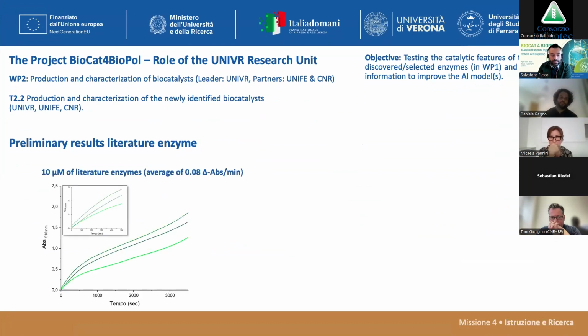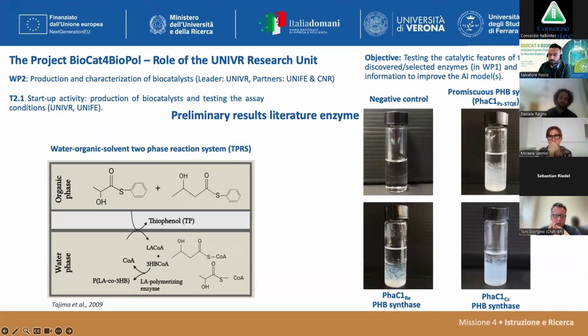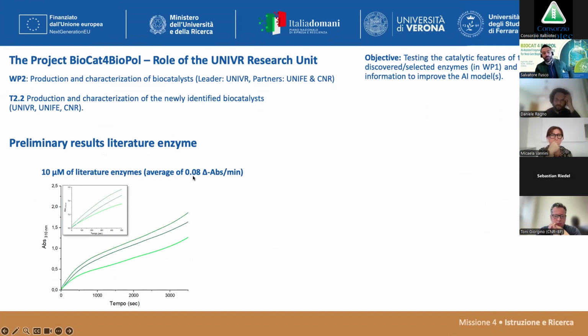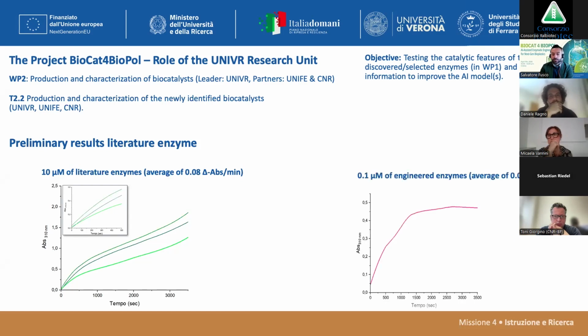The last thing I will show you is a preliminary result. We have tested one of these enzymes as it is, and we measured the velocity by measuring the turbidity of the reaction medium. Using 10 micromolar of the enzyme, as reported in literature, we found an increase of 0.08 absorbance units per minute. But then, thanks to Tony's group, we have engineered these enzymes, and by using 100 times less enzyme, we got just half of that increase. So the enzyme is likely to be maybe not 100 times faster, but several orders of magnitude faster.